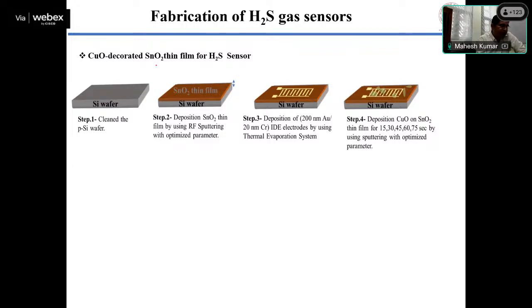We have deposited the tin oxide, and we found that tin oxide gives good sensitivity towards H2S, but it is not selective. So then we deposited some copper oxide as a decoration, and copper oxide has another problem. If you use pure copper oxide, because H2S is there and we are doing the measurement at 150 degrees centigrade, the copper oxide converts to copper sulfide, and copper sulfide is highly conducting, so it does not give any sensing towards the H2S. So that is the issue.